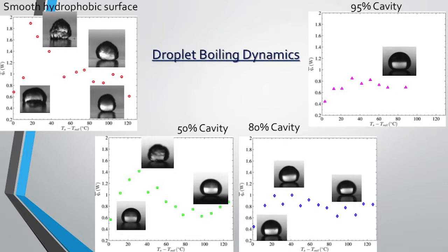This looks different for each and every one of the surfaces. So if I look at the smooth surface, and this is hydrophobic, so it's still water repelling, but it's smooth, you can see the boiling curve looks like it boils less and less. If I now have 50% cavity, so 50% in contact with the surface and 50% in contact with air, I get a little bit of boiling at about 40 C, and that's it. Otherwise, it just sits there. And at 80% cavity, so it's only in contact with 20% of the surface, you can see it kind of wiggling a little bit. That's the most we get. And then by the time I get to 95% of it being cavity, it just sits there.